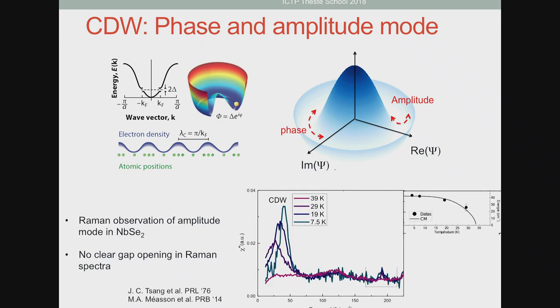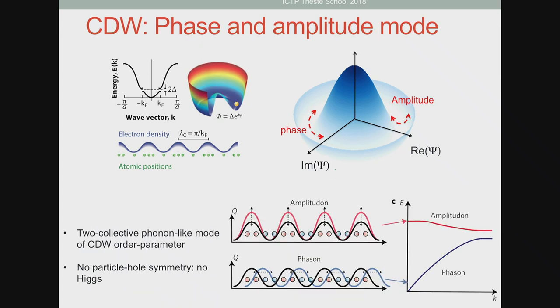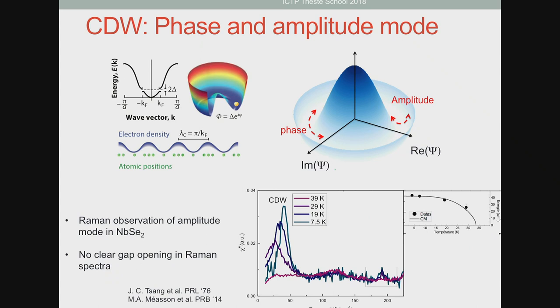But the key point is that this amplitude mode can be Raman active, so it can be directly seen in the Raman measurements. So here I show you Raman spectra as a function of temperature, and what you see is that when you cool down below the charge density wave transition, there is a new mode that appears. It's a relatively sharp mode. And this new mode corresponds to a phonon-like, yes.